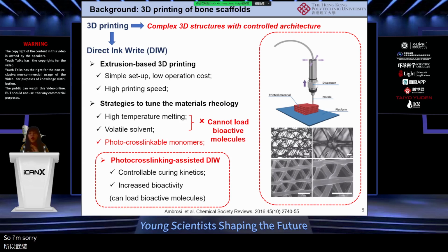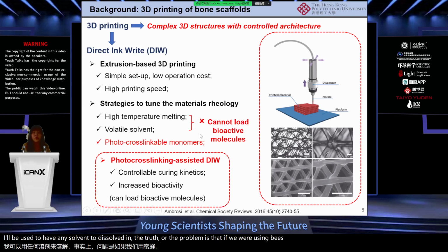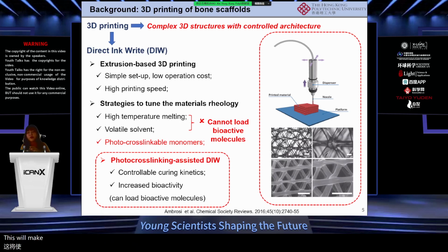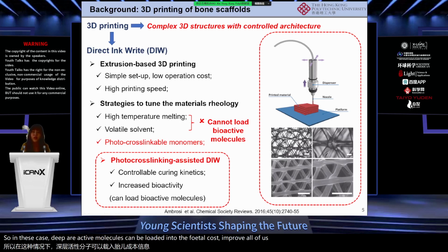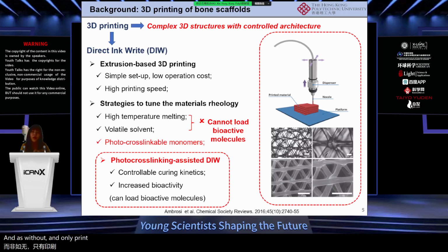We can make these materials liquid either by using a high temperature to melt the materials, or by using an organic solvent to dissolve the materials. The problem is that when we use high temperature or organic solvent, this will make the materials not able to load the bioactive molecules. So that's why we want to use photocross-linkable monomers. In this case, the bioactive molecules can be loaded into the photocross-linkable monomers and then squeezed out, and we print layer by layer, and then we can form these three-dimensional scaffolds.